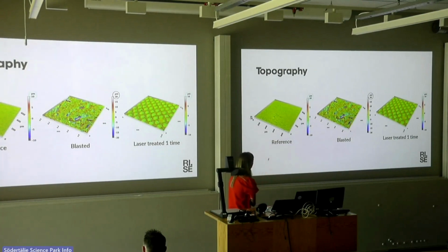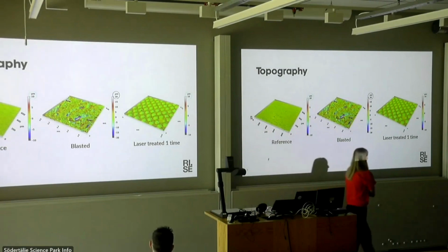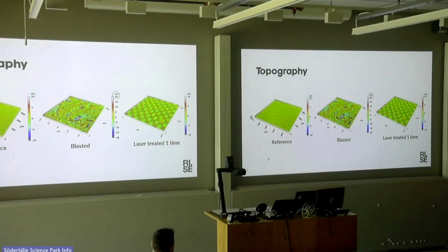If you want to create a microstructure or a certain structure, you have a well controlled process. It will be the same every time you do it, very precise, compared to a blasted surface. Beware of the scales here; they're not the same. But here you have a structure, but it's homogeneous, and then a blasting surface is more irregular and also increases the surface area, but in a more unstructured way.